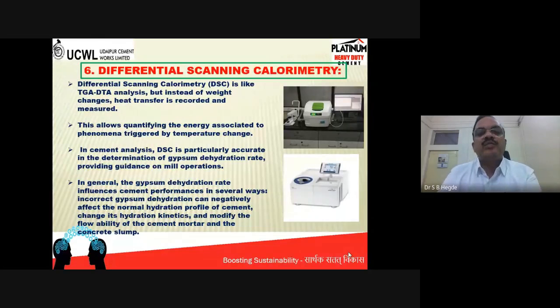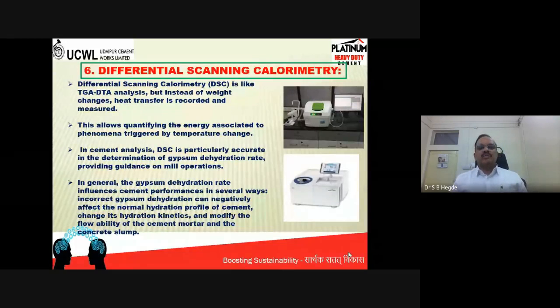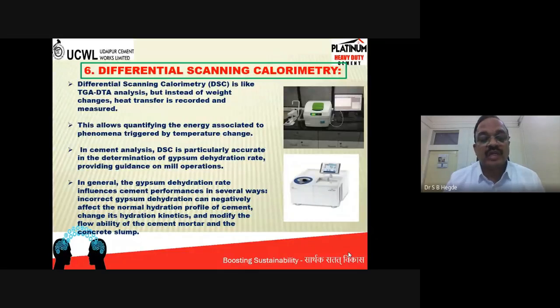Instead of weight changes, the heat transfer is recorded, and you can come to know about the hydration kinetics of the cement and even gypsum dehydration, because gypsum dehydration is a very important aspect while we are producing cement, and is also very important from the application point of view. Gypsum, you are aware, is CaSO4 2H2O. When we are grinding the cement along with the gypsum in the cement mill, if the cement mill temperature exceeds more than 120 degrees centigrade, this gypsum CaSO4 2H2O will be reduced to CaSO4 half H2O, and it will create a lot of problems in the concrete, whether it is false set or flash set, and slump loss, flowability, etc.